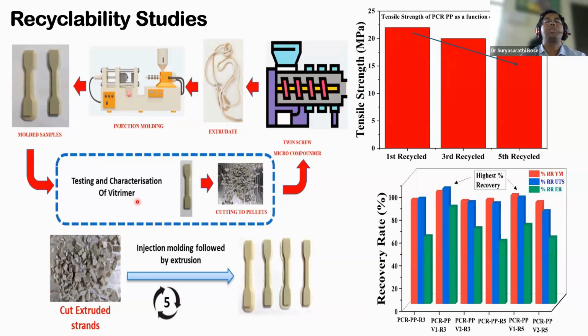Whereas when we use our own PCR containing this special oil, we see that even after the 5th cycle of recycling, there is highest recovery, which means we were able to restrict this drop in mechanical properties and also restrict the increase in MFI. And that is because the homo-cross linking that was introduced together with the covalent adaptable network helped us to recycle the material for at least 5 times to show that the properties don't even change, and therefore they can be put to multiple uses.